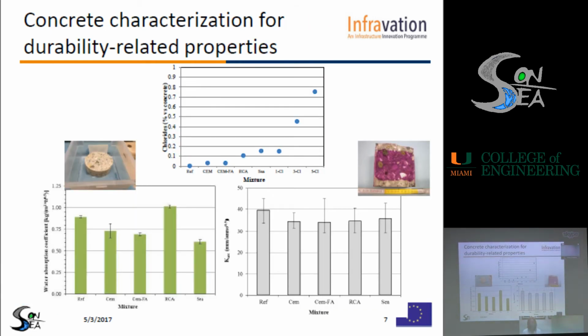Other tests were performed in order to investigate the durability-related properties. This slide just summarizes some of the tests which were performed. In the figure above, the chloride content measured on the different types of mix is reported. In the figure on the left at the bottom, the water absorption coefficient is reported as a function of the different types of mix.